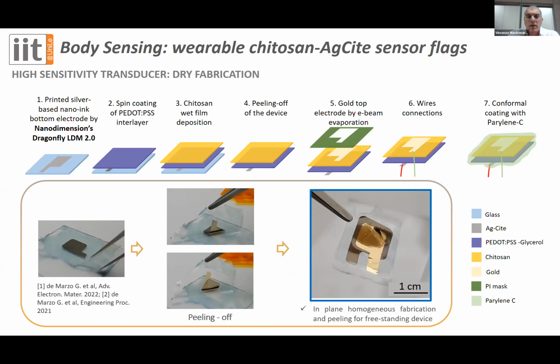The last step of the process consists of conformal coating of the sensor by a polymeric parylene C layer that makes the final sensor completely electrically isolated and waterproof. So the critical point of this process is the detachment of the sensor from the glass substrate.